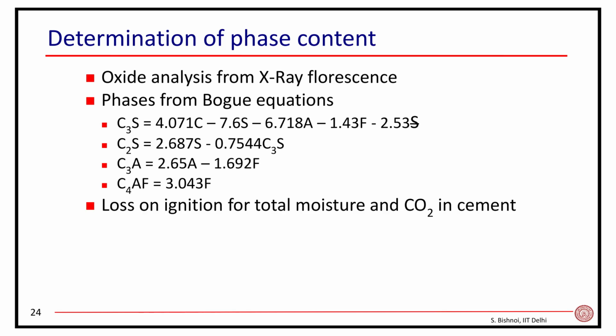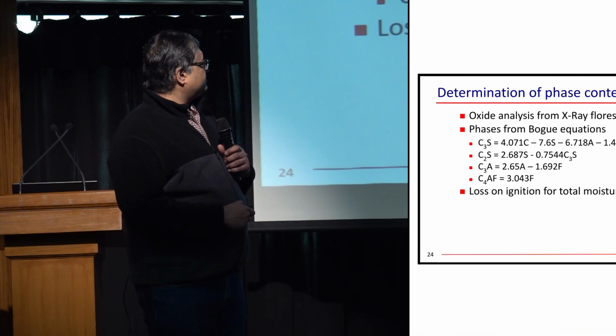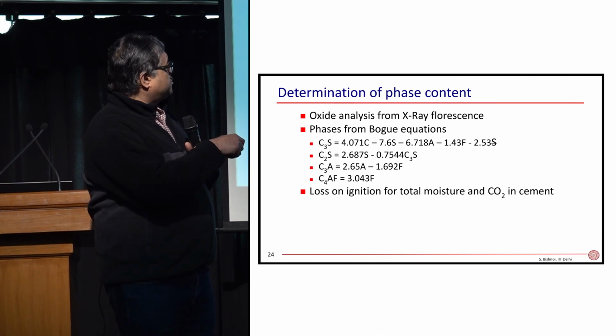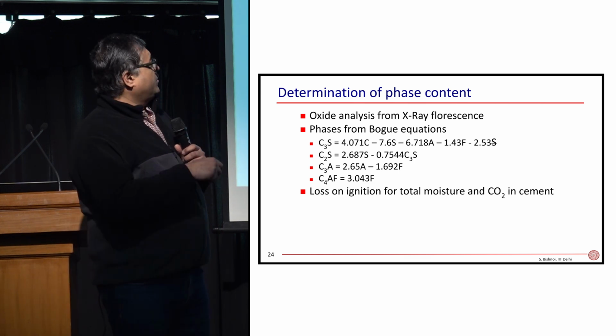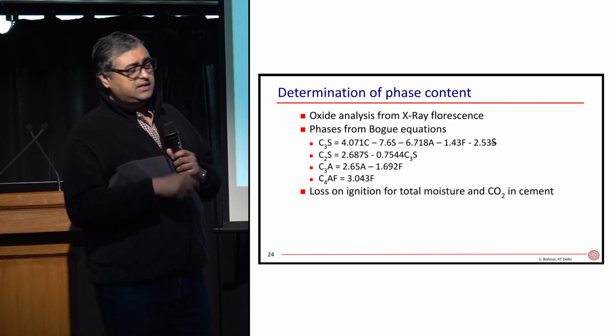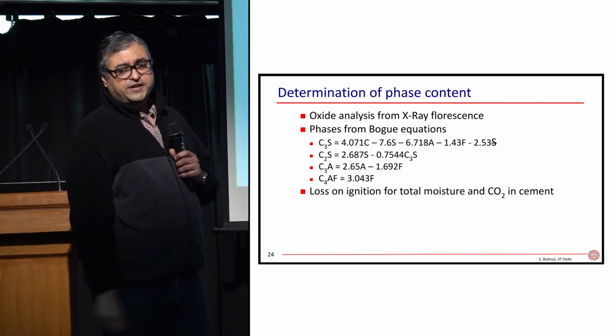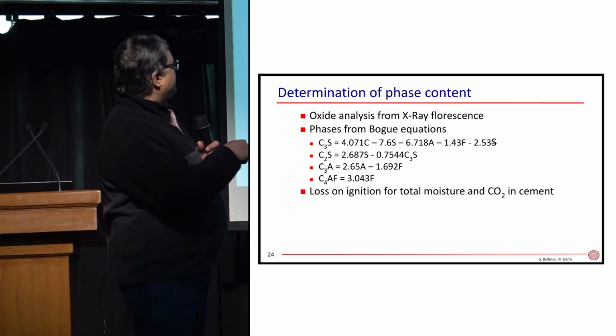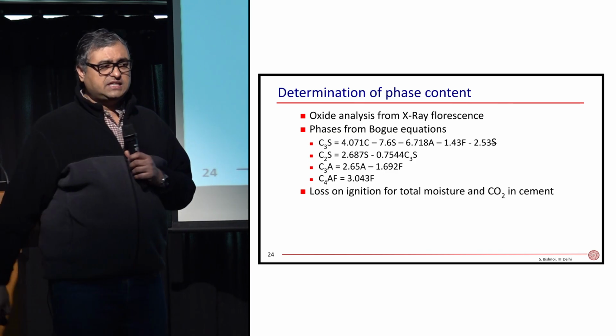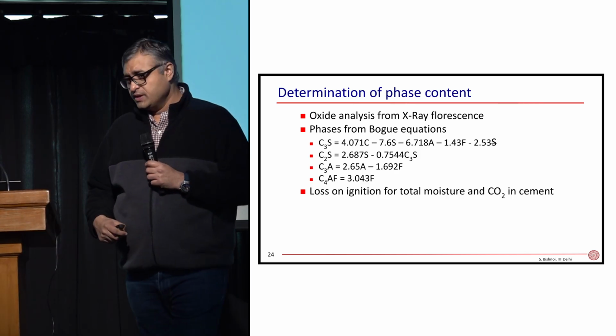And he said that if you know the amount of calcium that's there in the cement, if you know the amount of silicon, the amount of alumina, the amount of iron, the amount of sulfate in your cement, you should be able to back-calculate how much C3S, C2S, and so on is there.